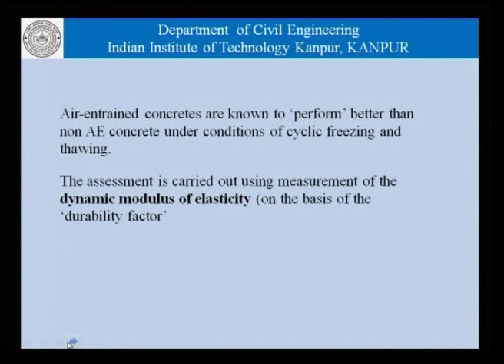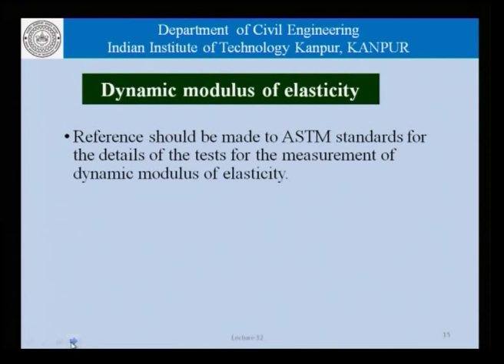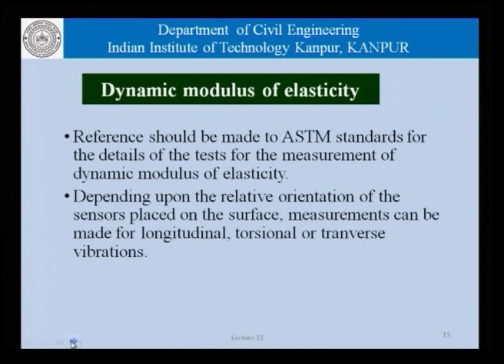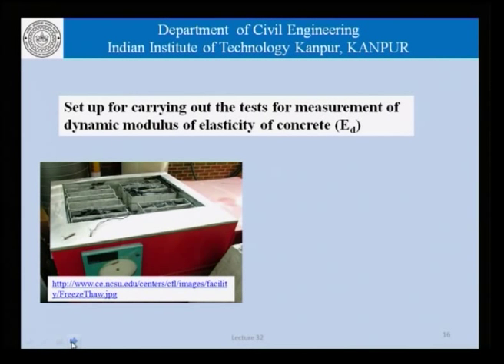The assessment of whether a concrete is durable or not is carried out based on the measurement of the dynamic modulus of elasticity, on the basis of a durability factor. What these terms are, we will probably see presently. As far as the dynamic modulus of elasticity is concerned, you should read the appropriate ASTM standards for the details of the test. Depending on the relative orientation of sensors placed on the surface, measurements can be made for longitudinal, torsional or transverse vibrations. This will become clear once we see how the measurements are done. But before that, let us see how the test is actually carried out.